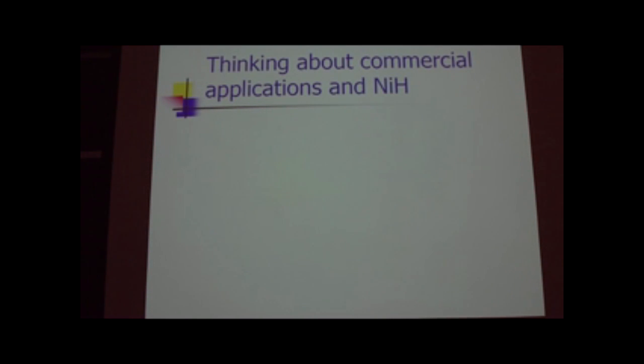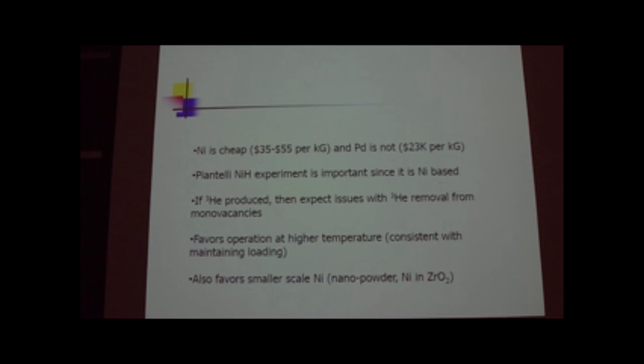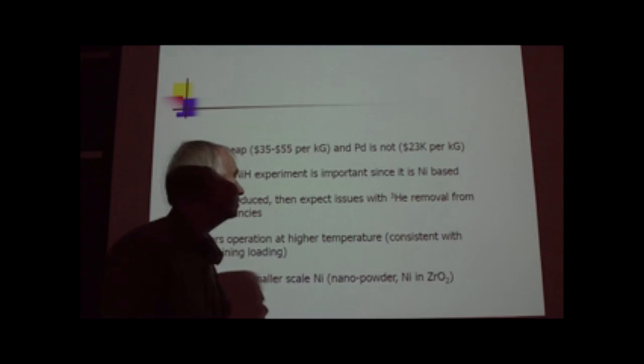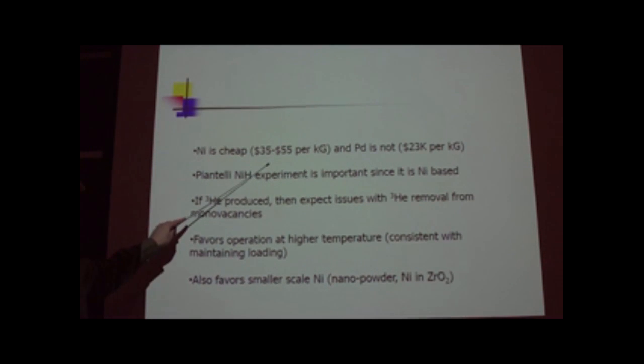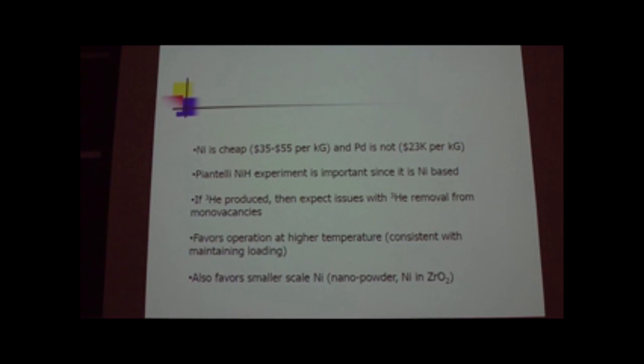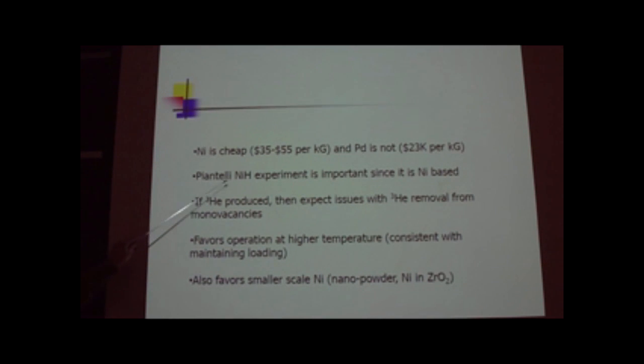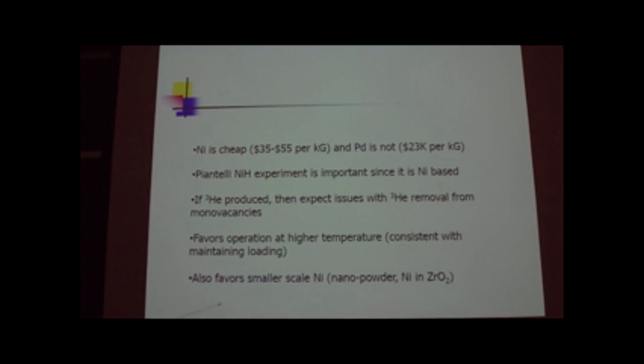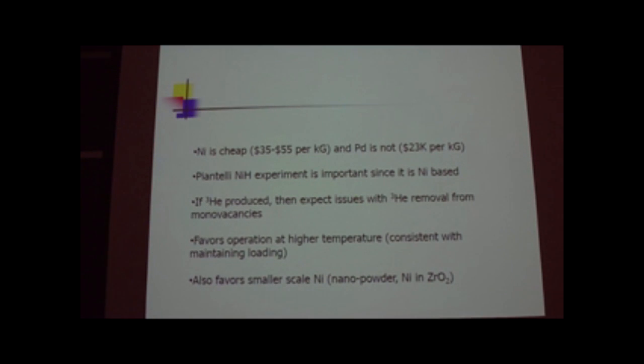Okay, my last topic, I want to think a little bit about commercial applications in nickel hydride. So the importance of the nickel hydride is that nickel is cheap, palladium is not. The Piantelli experiment is important because it's a significant amount of excess heat, nickel-based. If you believe that helium-3 is made, then you have the same issue for helium-3 removal as in the helium-4 case with palladium deuteride. So this favors higher temperature, and in parentheses, at higher temperature you have issues with loading, so you want to make sure that at the temperatures you go to, you can still get the loading you need.